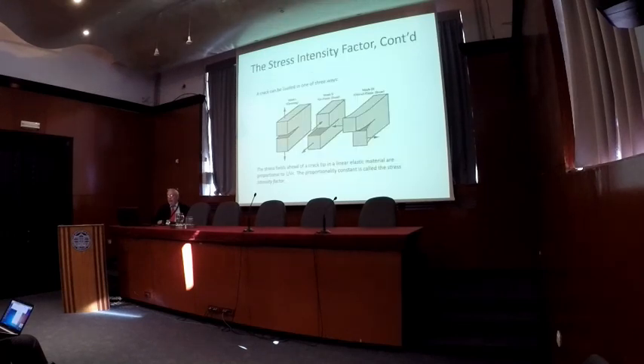Anyway, he started out looking at a stress-based approach. In the stress-based approach, you need to consider three geometries of loading. The first one is called opening mode, or mode one. That is when the stresses and loads are perpendicular to the crack plane and it pulls the crack apart. And that's the most important one. About 90% of all work in fracture mechanics is with mode one. Another mode that's sometimes considered is mode two, which is called in-plane shear or sliding. That is when the loads are parallel to the crack, not perpendicular, but they're in the plane of the structure. And the last one is mode three, which has loads parallel to the crack, but out of the plane. That's a tearing mode. So we would be dealing here mostly with mode one, the opening mode.